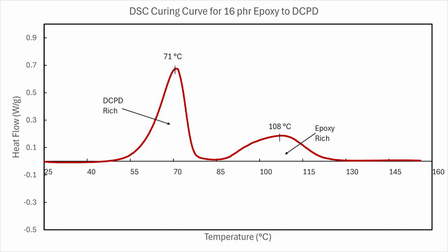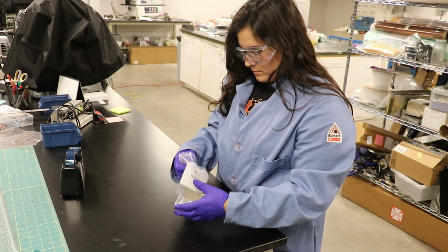We used differential scanning calorimetry, or DSC, to investigate the curing kinetics of the down-selected resins. DSC revealed two curing peaks. The first peak, centered around 71 degrees Celsius, is associated with the curing of DCPD, and the second peak, centered around 108 degrees Celsius, is associated with the curing of the epoxy. When we heat the mixture to 150 degrees Celsius and hold, both materials cure into network structures that may or may not have separated phases. We prefer to see a single phase in which properties will be homogeneous.